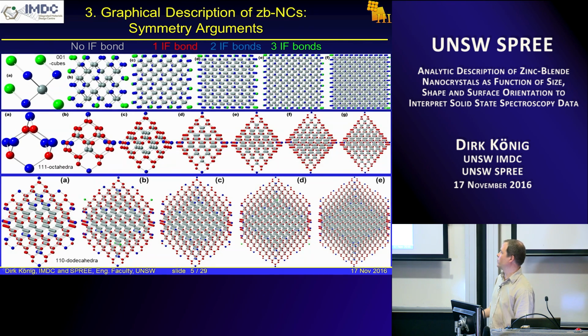And these are also complex because, strictly speaking, this is not 1 number series, but 2 number series. So you have an odd series and an even series. And you can see the even series has 1, 2, 3, 4 atoms which are exactly at the corner point between the 3 rhomboids. And so they have 3 interface bonds, whereas the odd series doesn't have that. So that again is from the even series. You got two green atoms here with 3 interface bonds, another 2. So that's a bit more complex.